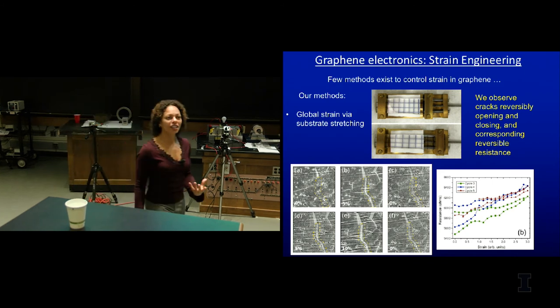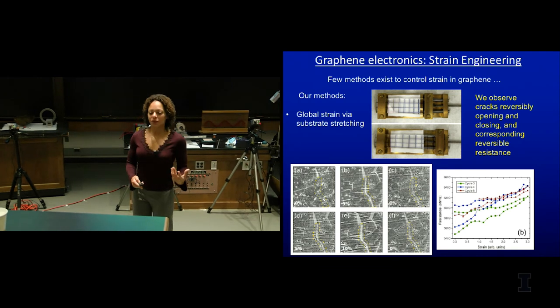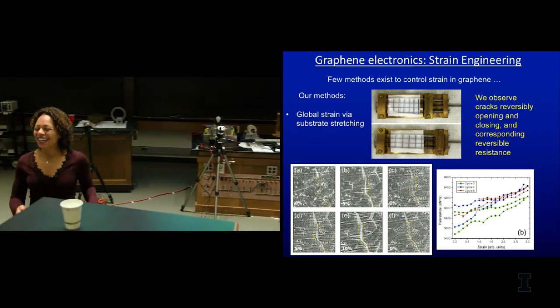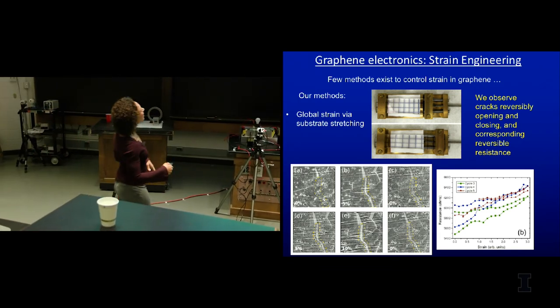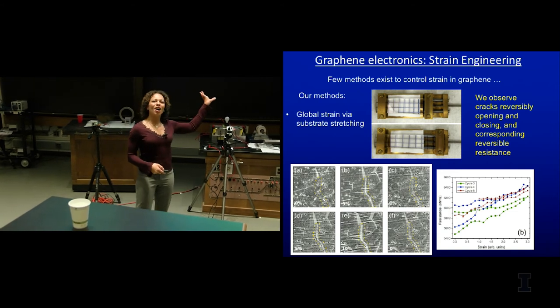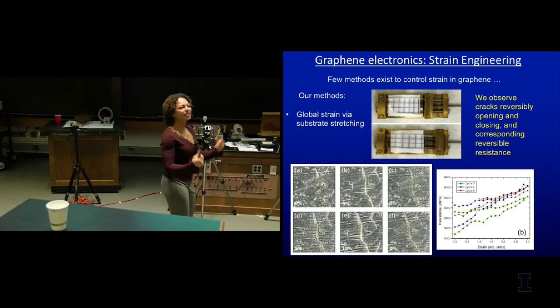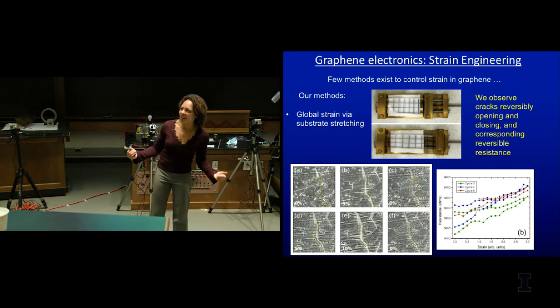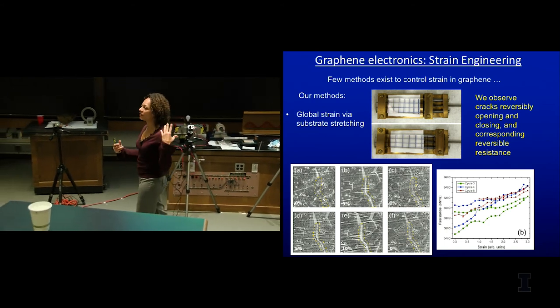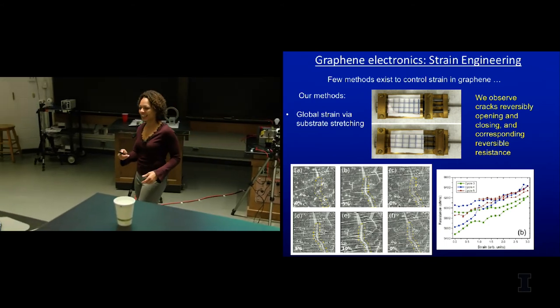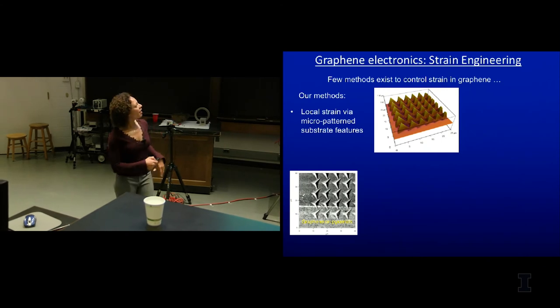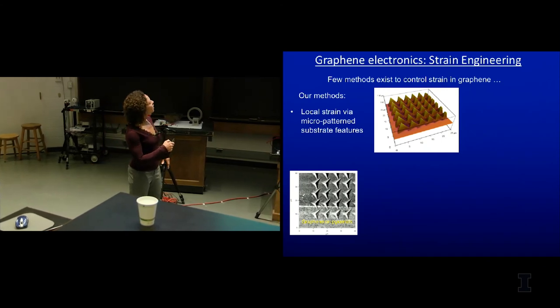And so that's not that interesting, but at least we did it, and it was fun, and you could see the cracks open and close, and this is one of the things you want to know if you're going to make devices out of it. What happens if it cracks, right? Does it totally change the electronics? Is it still robust? And in this case, we found out that it is pretty robust, even if it's cracking, right? We then put graphene on top of substrates where we nano-patterned them.